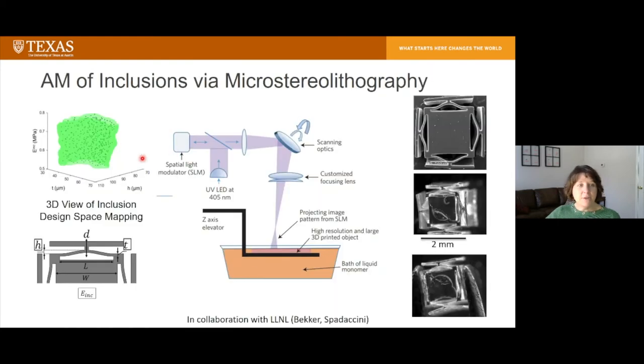So we make these inclusions using microstereolithography, which is a process that was developed at Lawrence Livermore National Lab, where they can build really small features on the order of 50 microns, and they can build it over a large area of several inches. So we take a look at our design space here, and we have a mapping of it, and we can pick good designs to fabricate.